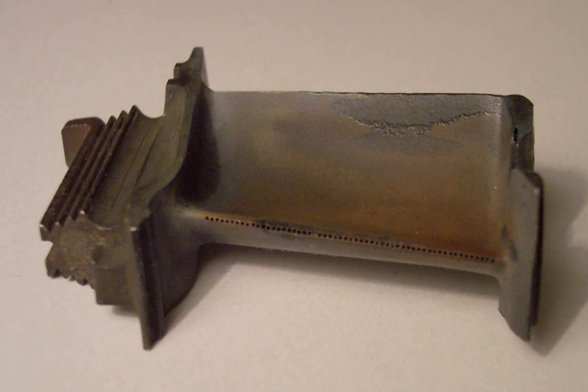The discs of the high-pressure turbine, which are near the central hub of the engine, are polycrystalline. The turbine blades, which extend radially into the engine housing, experience a much greater centrifugal force, necessitating creep resistance. As a result, turbine blades are typically monocrystalline or polycrystalline with a preferred crystal orientation.